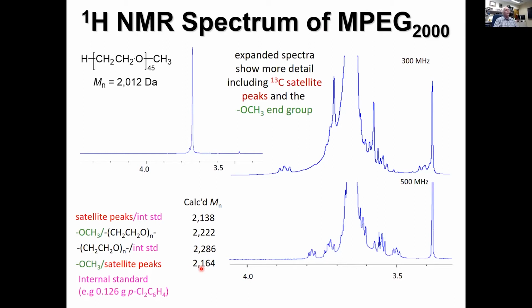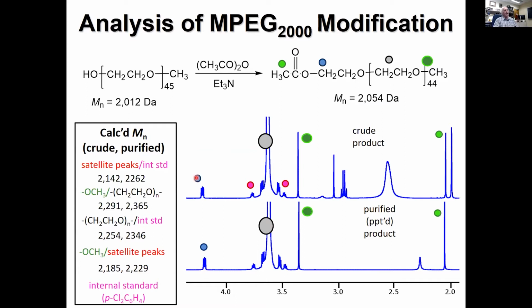If you then go off and take this polymer and do the chemistry I described where you put a functional group on the end, if it was a starting polymer that had an OH and an OH, it would be hard to tell how many esters we actually added. When it's got an OH and an OMe, we can clearly integrate this peak and that peak of the ester. This is the purified polymer. So this peak of the ester, that peak of the OCH3.